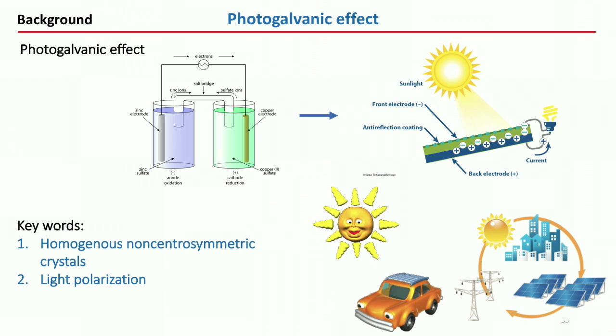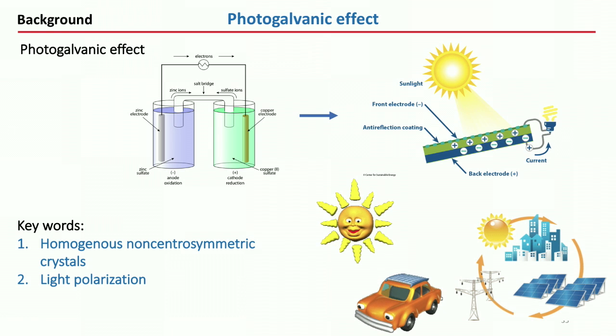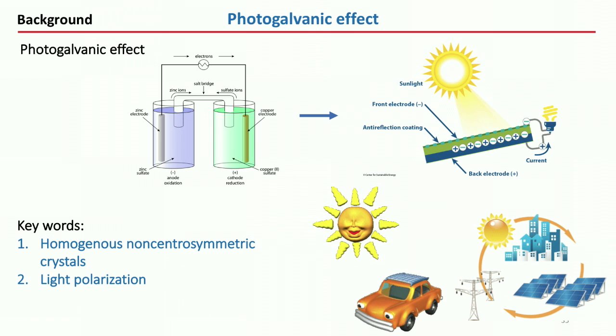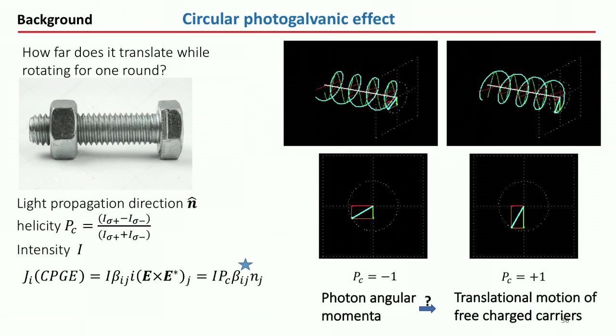So now the effect that I'm going to talk about is an equivalent of this, called the circular photogalvanic effect, where the idea is you can get this type of behavior, can extract current out of the system without having an interface and without applying any electrical bias. So there's no battery that we need, and there is no interface also to separate the carriers. So this solar cell behavior is a linear effect because of the presence of the interface, but when we go to a bulk system, then this effect is nonlinear.